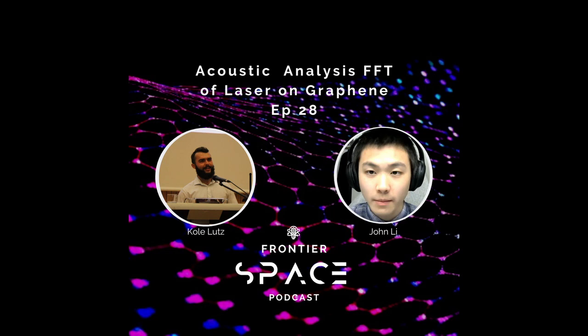Now, the thing is that computers with a microphone can hear a lot of frequencies and also have much better resolution than the human ear has. So not only was he able to show that the graphene that I was hearing when the filter came out correctly was the right stuff from my perspective, but he was able to show that different sounds actually corresponded to different products being formed, and different products have different morphologies as well as different spectral characteristics. And that is the basis of this paper.